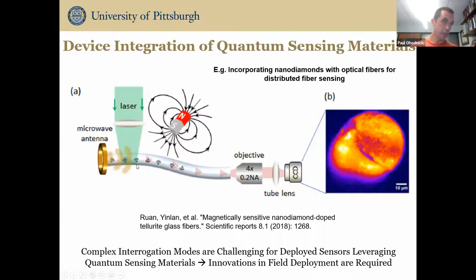And then it has local introduction of microwave energy by an antenna, which is placed in proximity. So based on this, they can measure the characteristic emission by the guided modes within the fiber, and then they can map that out with a CCD. So this is a really interesting piece of work. They can use it to measure local magnetic fields. But in terms of being able to do something like this all along the length of kilometers of fiber becomes a major challenge. So one of the key challenges moving forward is how do we rethink the way that we integrate sensing layers with these types of device platforms which are so practical for energy applications?